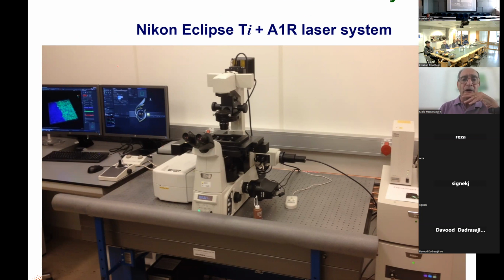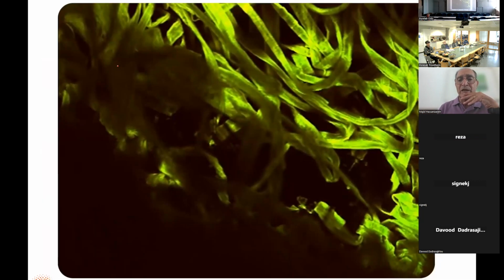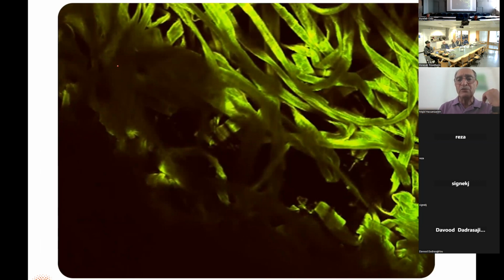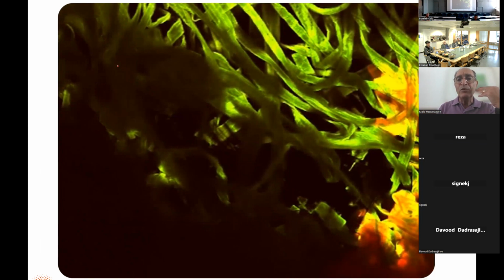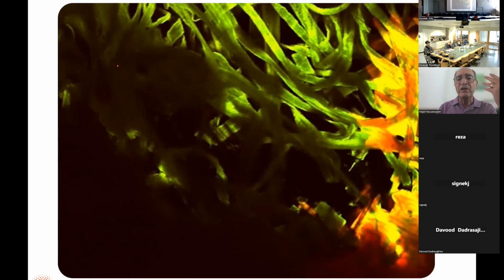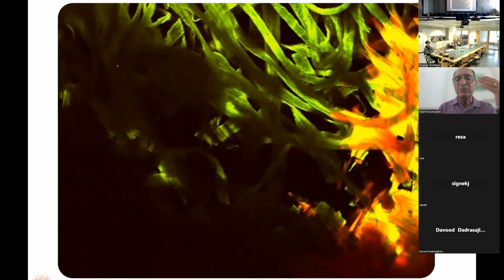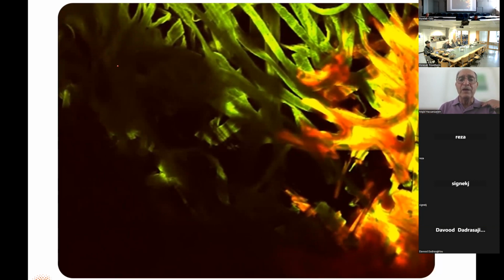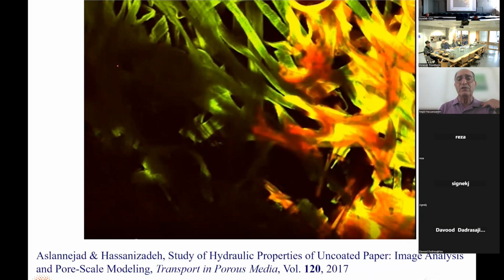Here is a Nikon microscope that we have used for imaging, getting images like this. What you see are the green fibers of the fibrous layer, and then we are introducing some fluorescent dye from the right-hand side. What you see is that there are two fronts. See, the redder the color is, the higher the moisture is. And you can see that the fibers become red, and the space between fibers will actually become more saturated afterwards. So it's a sort of two-domain invasion of this ink into that fiber. And you can see that here very clearly. There are really two different fronts.